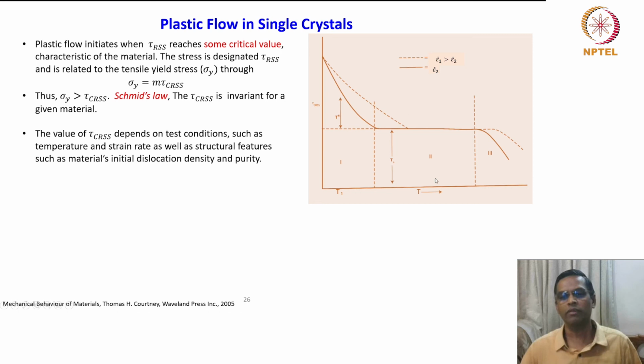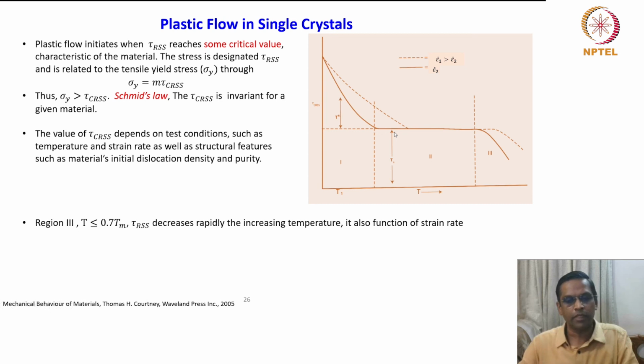So what does it show? It's very interesting actually. You can see that this plot exhibits almost 3 regions: region 1, region 2 and region 3. And what are the critical points to be noted? In region 3, where T is less than or equal to 0.7 Tm, tau CRSS decreases rapidly with increasing temperature. It is also a function of strain rate. In both strain rates the curves look different, so it is sensitive to strain rate as well.